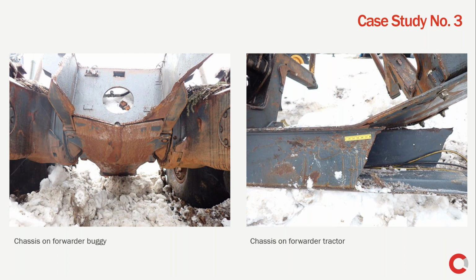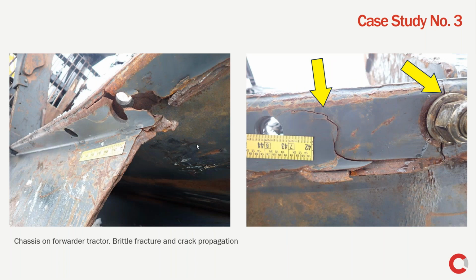The temperature at the time of the loss was around -30 Celsius, and that's going to come into consideration later on during the investigation. But the first thing that comes to mind when looking at this fracture is how brittle it looks, how far the cracks propagate from the point of origin, and how jagged they are.